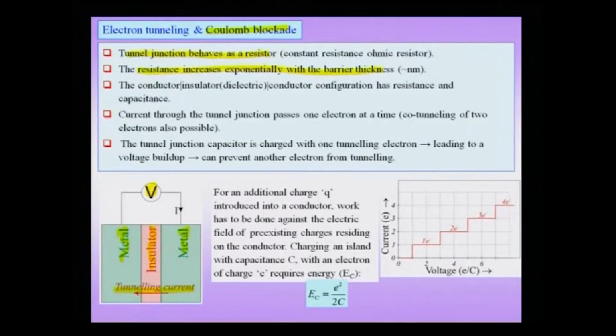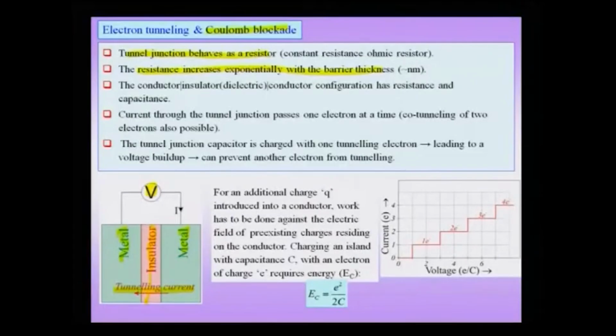And now I am talking about barrier thickness which is very small, of the order of a nanometer. If this insulating barrier becomes large, then I would find that there is no current transported from this green metallic region, which is shaded green, to the next metallic region, which is also shaded green. So, for this kind of tunneling current to take place, the thickness of this barrier, the insulating layer, has